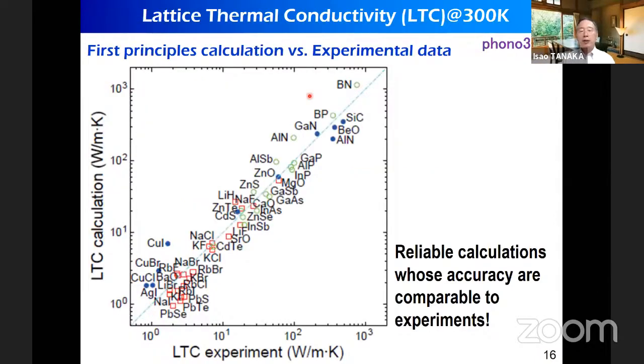This is the result for the lattice thermal conductivity by this calculation. Lattice thermal conductivity is abbreviated to LTC. So this is the experimental data obtained from handbook, and this is our theoretical result at room temperature. And there are altogether something like 50 to 60 compounds shown here. And you can see that most of the data points fall on this diagonal line.